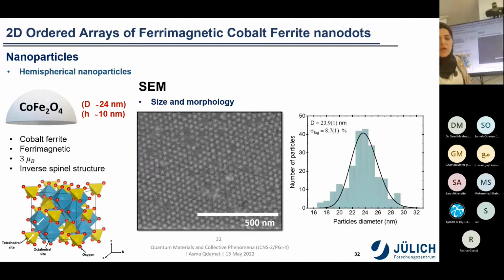Here we can see the scanning electron microscope image for this monolayer, and we see that it has almost regular spherical shapes, with some areas where there are defects and we can't see any particle. I analyzed this scanning electron microscope image manually to get the size and the size distribution of the particles, and we see here from the lognormal distribution that we have particles around 24 nanometers with a size distribution of around 8%.